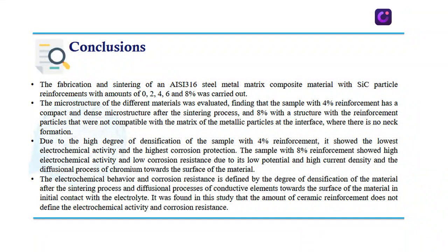As a conclusion, the fabrication and synthesis of an AISI 316 steel matrix composite material with a silicon carbide particle reinforcement of 0, 2, 4, 6, and 8% was performed. The microstructure of the different materials was evaluated, finding that the sample with 4% reinforcement has a compact and dense microstructure after the sintering process, and the 8% sample a structure with reinforcement particles that were not compatible with the metallic matrix at the interface, where there is no neck formation.